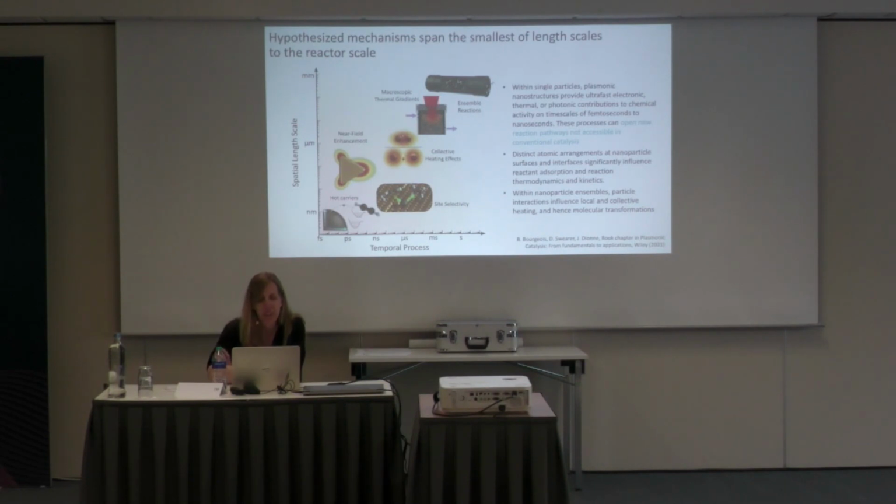So first of all, the palladium gold itself has its own plasmon resonance, just by virtue of the coupling between the antenna and the reactor. The hydrogen leaving and entering the palladium changes the bulk plasmon resonance, but it doesn't change the gap plasmon resonance.